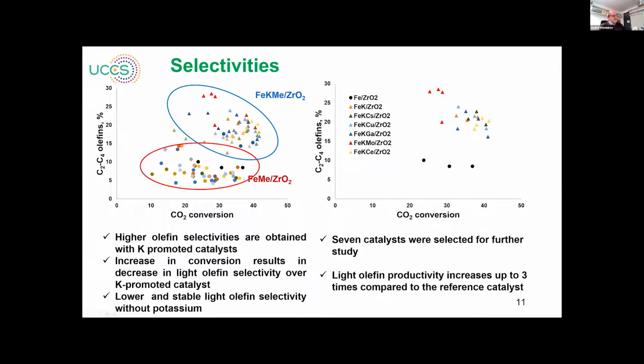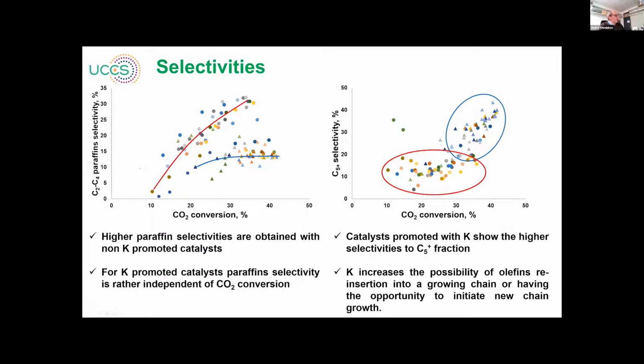And then after analysis of this data, we selected the most efficient catalyst. For this catalyst, we did a lot of characterization to understand why the catalysts are good. So this is a reference one without any promoter. This is with potassium, and these other catalysts contain cesium, copper, gallium, molybdenum, cerium. So these catalysts correspond here to the top part of the dependence of selectivity on conversion. Then the results were obtained for paraffin selectivity.